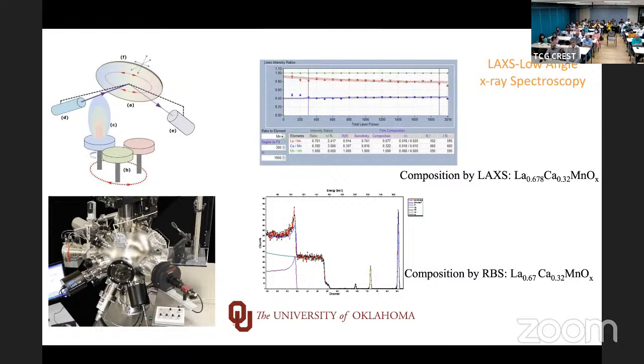So now what we do is we have an electron beam that essentially impinges on the surface, and this is something that we use called reflection high energy electron diffraction to measure the film structure and so forth. But this electron beam also generates X-rays, right? And people have been struggling to use these X-rays to measure film composition because they're characteristic X-rays. No one figured out how to use it, and that's because of various scattering phenomena in the film.